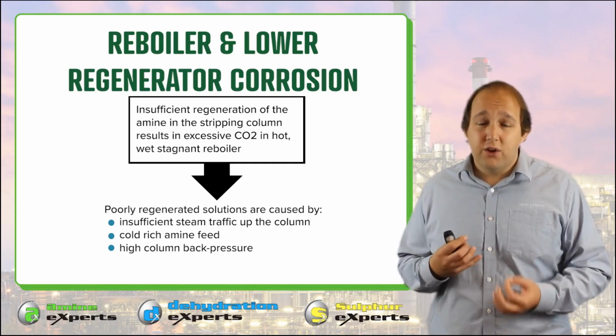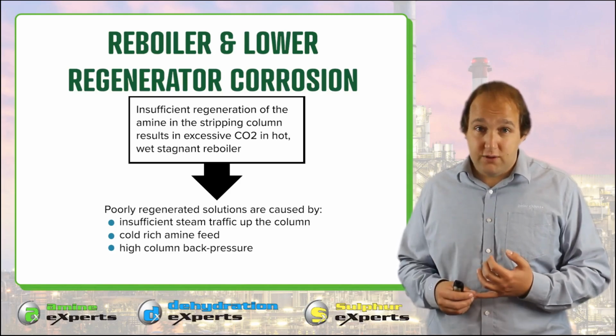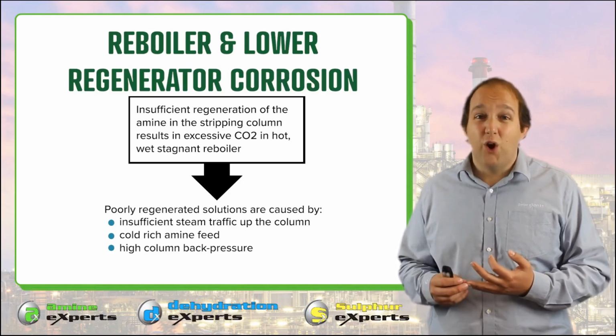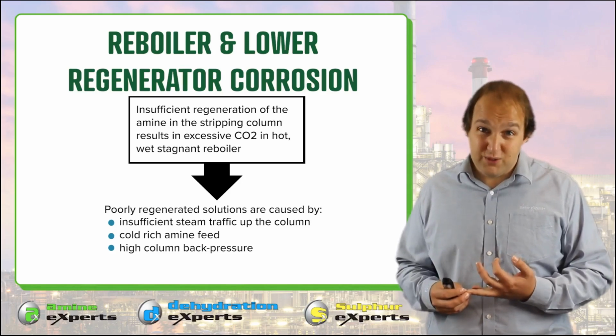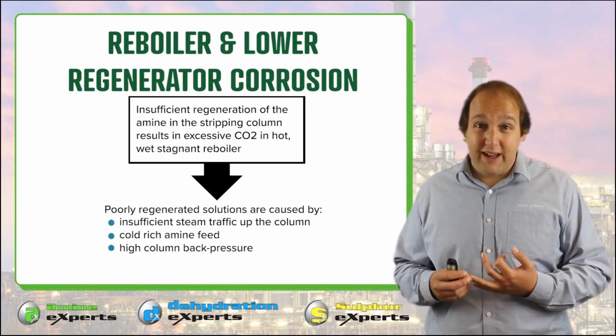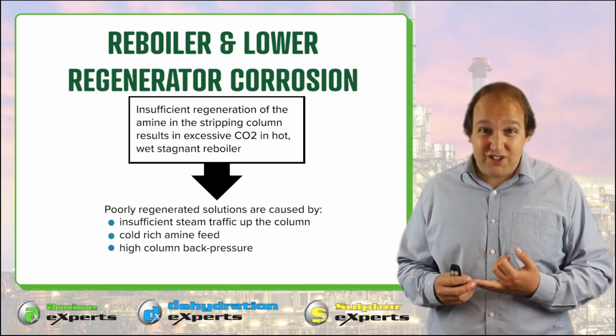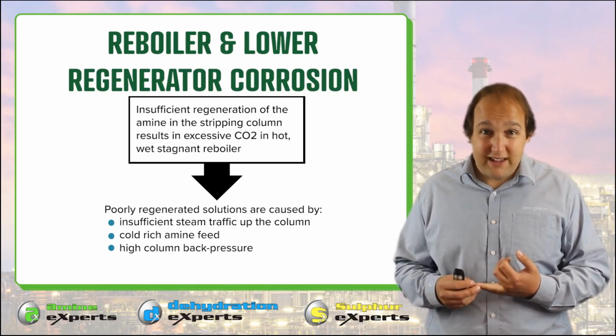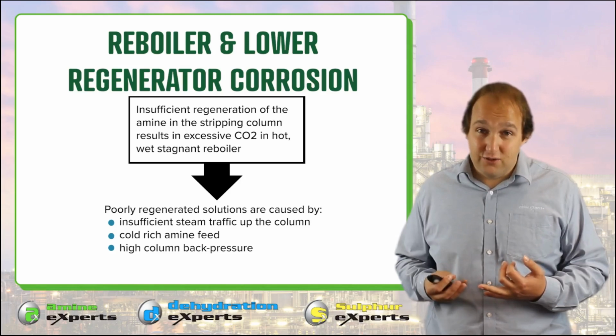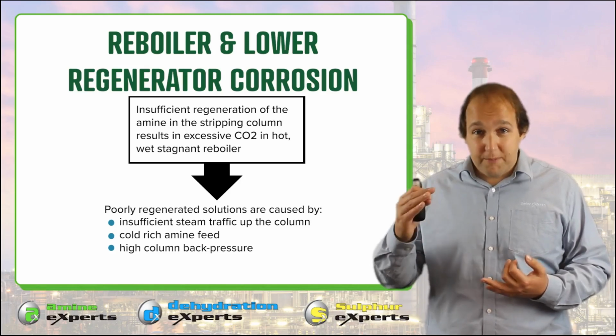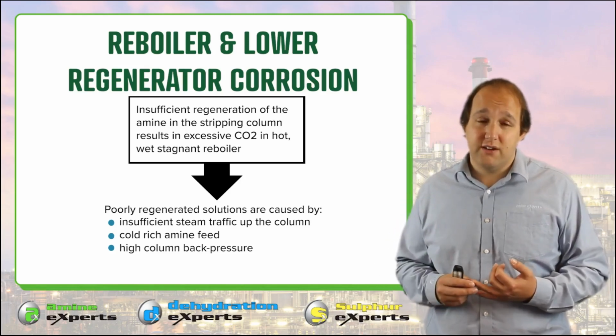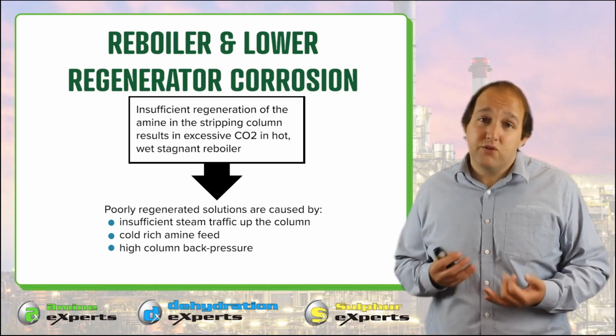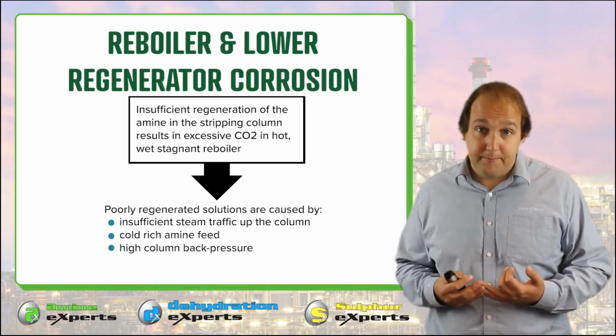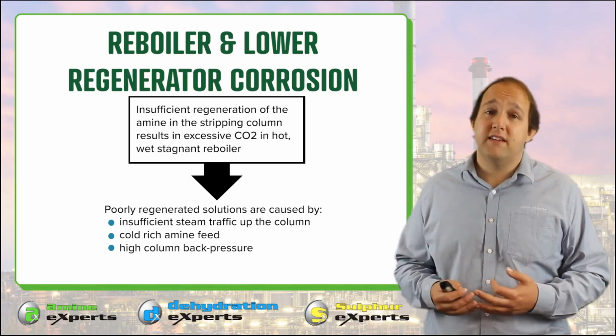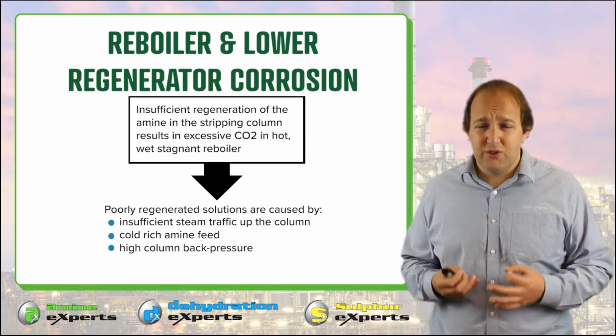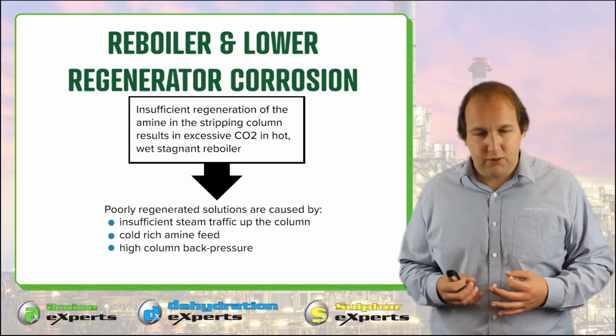So this really occurs when you're not putting in enough heat duty, and it can also occur when there's cold, rich amine being fed to the column. If you have a very inefficient or undersized or fouled lean-rich exchanger, you can send cold rich amine, and that will use up heat to heat it up, and your top couple of trays in your regenerator column will then not be doing stripping, they'll be heating the amine up. It could also take place as a result of running the regenerator column with too high a pressure, though this is a little bit more unusual.